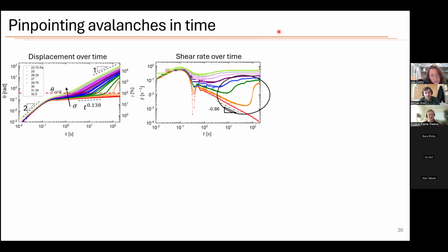So we have, as part of the study, introduced a new term to help understand this, which we call spurt. And spurt is defined as the second derivative of basically the strain acceleration over the shear rate, or the shear acceleration over the shear rate. And this is interesting because it looks like it should be an acceleration overall. And there's inertia earlier in the system, which gives the t-squared dependence earlier on. But what we're actually measuring with this term is how fast is the rate of change of the shear acceleration to the shear rate. And so we can write exactly the same thing in a different form, where here we're taking d shear rate dt, which is the top term here, or we can write it using logarithm form. These are all equivalent.